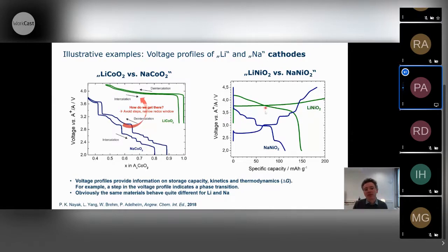The same thing can actually be seen for lithium nickel oxide and sodium nickel oxide in comparison. So also here, in the case of sodium, you have this staircase behavior, and in the case of lithium, you have a largely sloping potential. So the question is, how do we get from here to there?